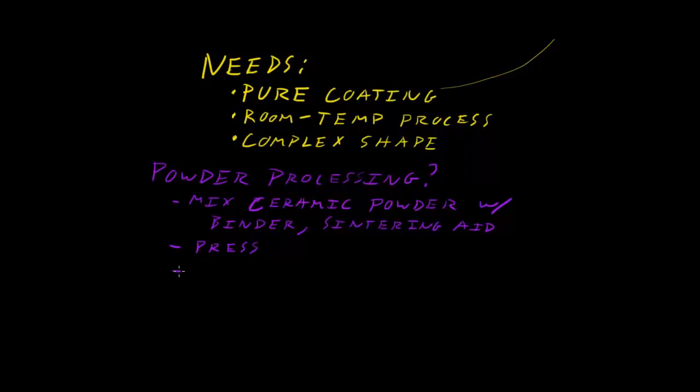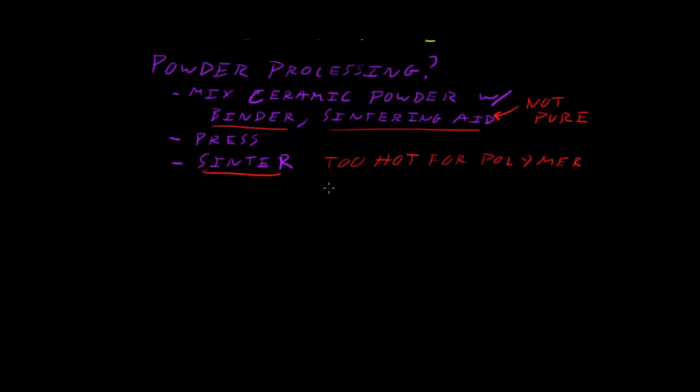You press all this together, and then you sinter it in order to bond, or to get all the powders to stick together and sinter. Now, unfortunately, binder, sintering aid, that's not pure. You don't have a pure ceramic anymore. And sintering is way too high of a temperature for your polymer to survive, so powder processing is out.